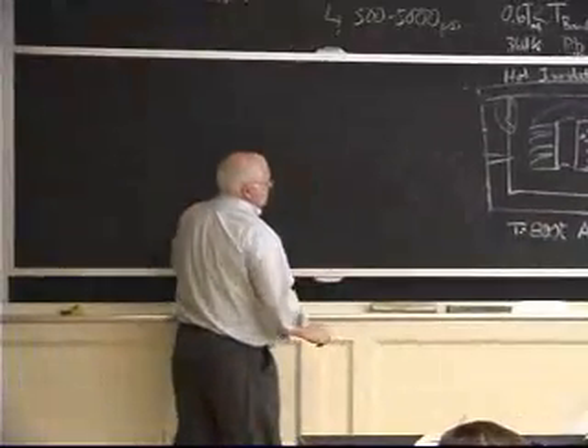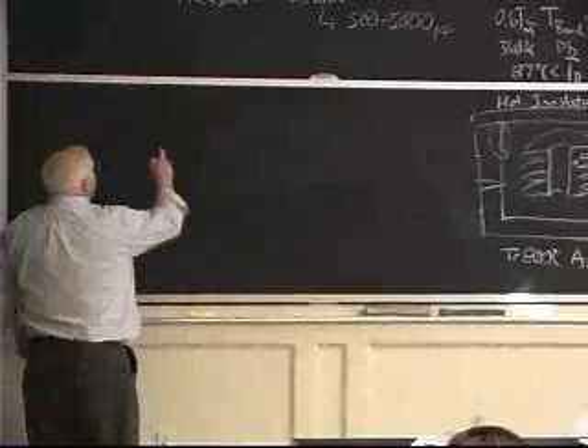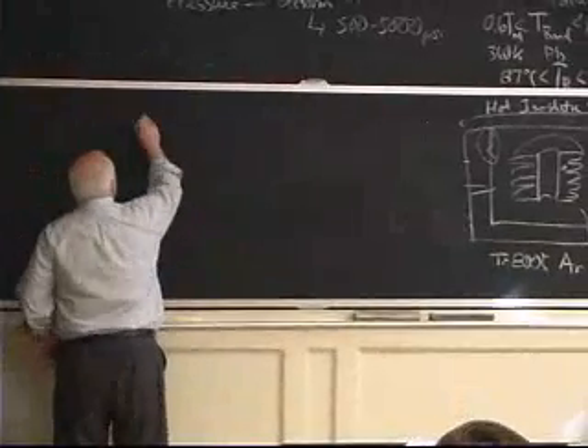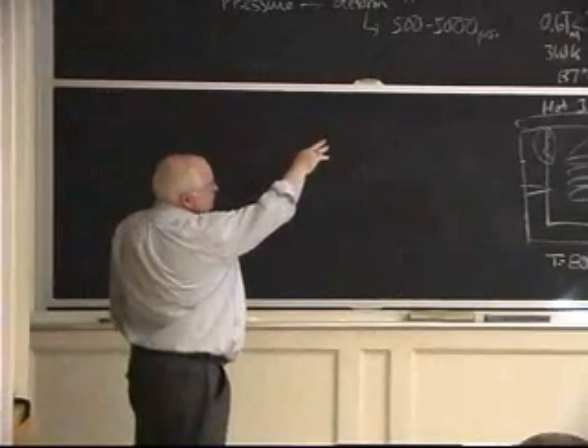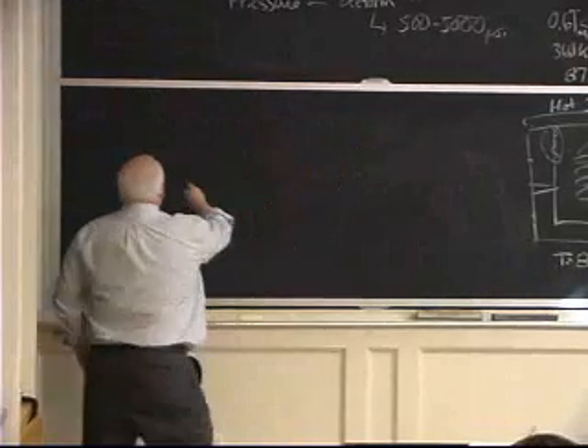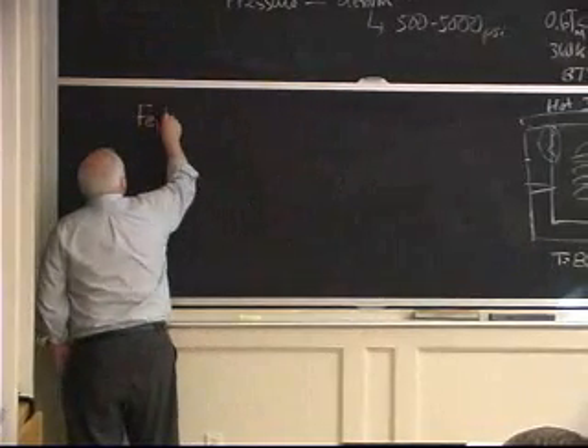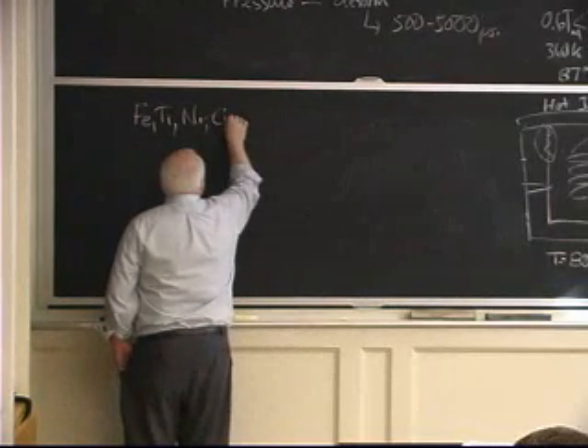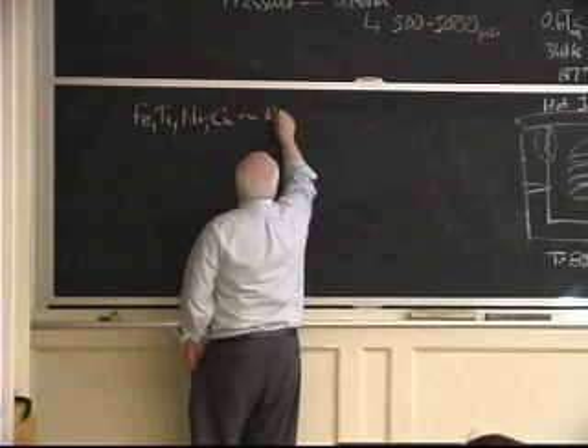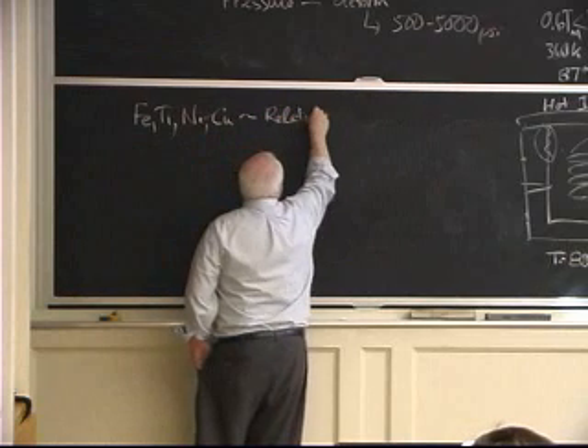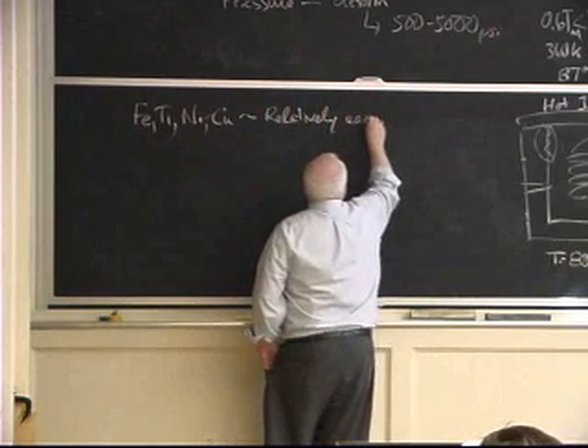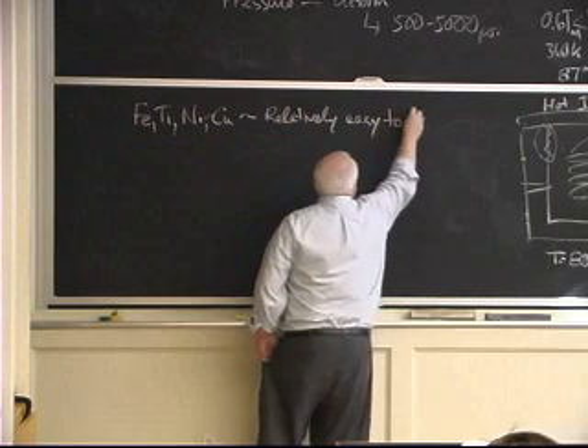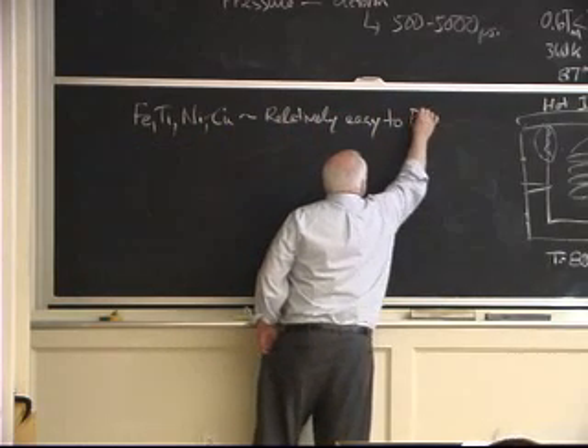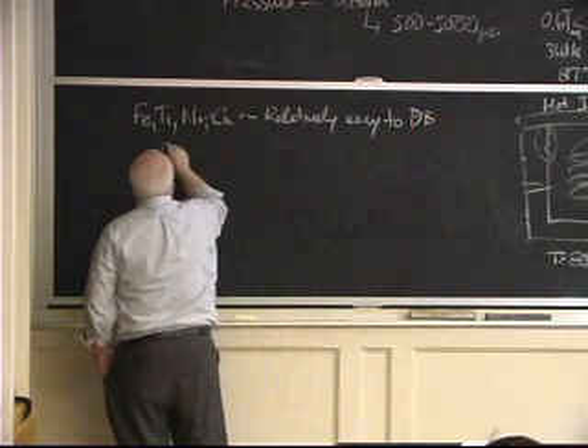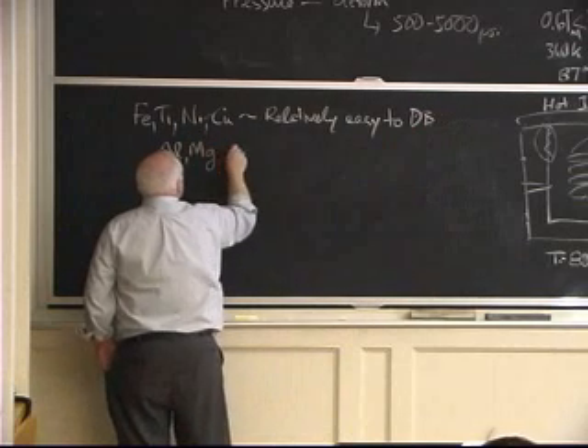The problem is, only certain materials will dissolve away. Another criteria is we've got to diffuse away our contaminants. Well, it turns out iron, titanium, and nickel, and to a certain extent copper, are relatively easy to get a near perfect bond. Talking about diffusion bonding here. Things like aluminum and magnesium, very different.